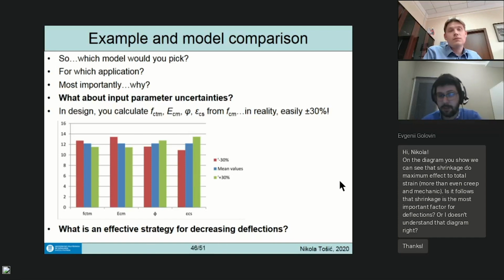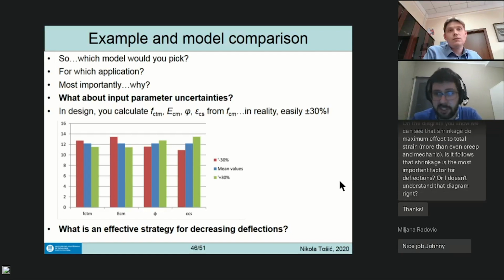Then think about an effective strategy for decreasing deflections. Is it increasing concrete strength? Probably not going to make much difference, as the modulus isn't going to change much. Are you going to add tensile reinforcement - is that going to help? Or are you also going to add compressive reinforcement? If shrinkage is the problem like here, adding an equal amount of compressive reinforcement will eliminate the curvature from shrinkage completely. So how much does that cost? Is it effective? How are you going to distribute that reinforcement, and so on?